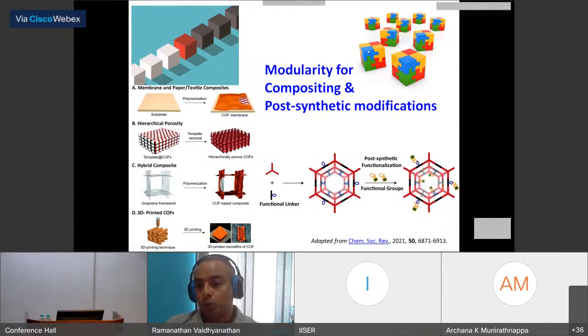And for example, this blue could be a hydrophobic unit. The yellow could be an amine-containing unit, very favorable for CO2 binding. The green could be something that controls the polarity of the groups and so on. So you can have different functionality within a single unit if you take this modular approach. And for example, if you introduce a hydrophobic unit, that becomes advantageous for developing coatings on bulk materials like paper, textiles, and so on. And that makes the paper and textiles hydrophobic, which means you have introduced a property which is not inherent or intrinsic to the paper and textiles by using these COFs in a very facile manner. You can simply paint this modular COF onto a paper or a textile.